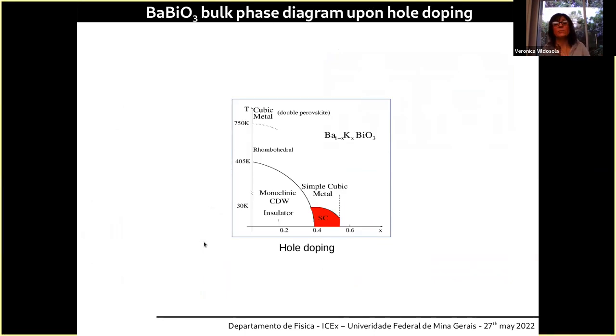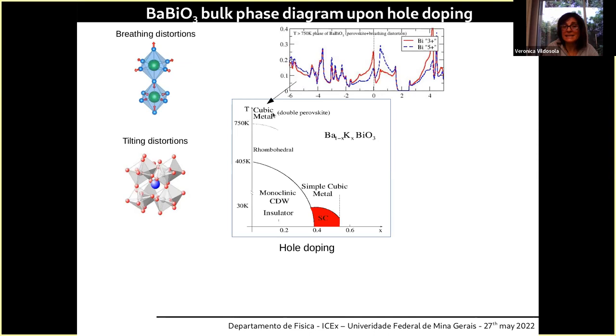So the barium bismuthate phase diagram is very rich. Here you can see the temperature versus hole doping phase diagram. If you go to high temperatures and low doping, the system is a cubic metal. It is a cubic metal, but in a double perovskite way. In this high temperature phase, if we do the calculations for the crystal structure that this system has at these temperatures, we observe that it is, of course, indeed metallic, but we have some incipient charge disproportionation, where we start to observe some difference between some bismuths that have more empty states than full, and the other ones, the blue ones, that have more full states than empty.